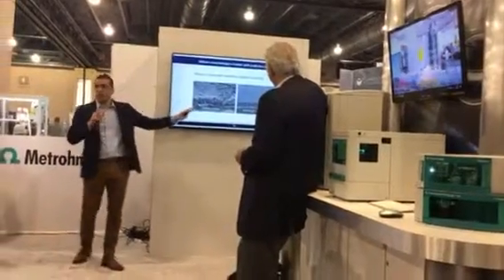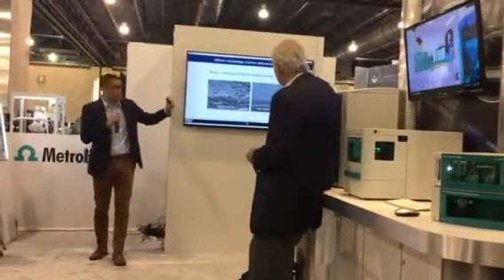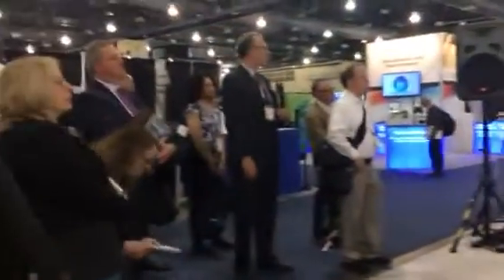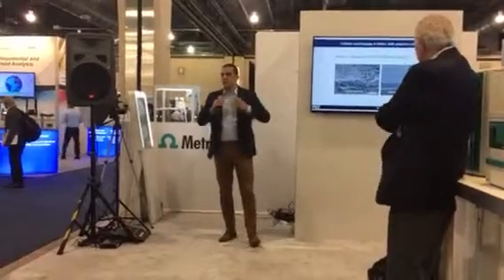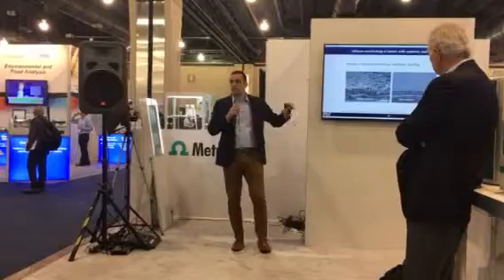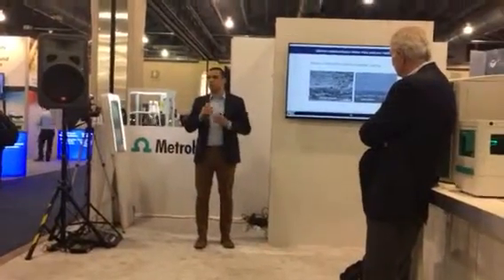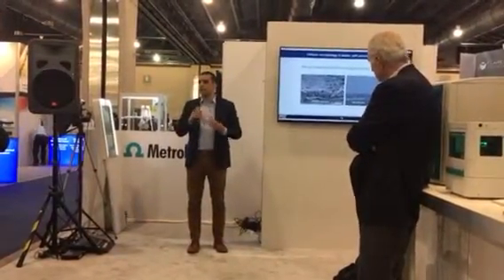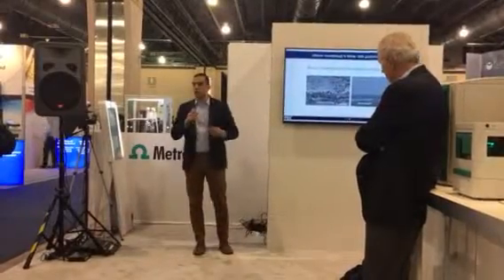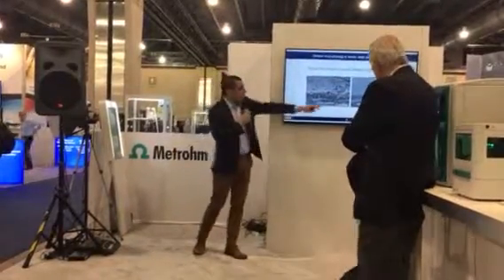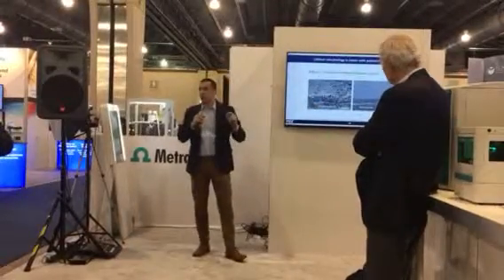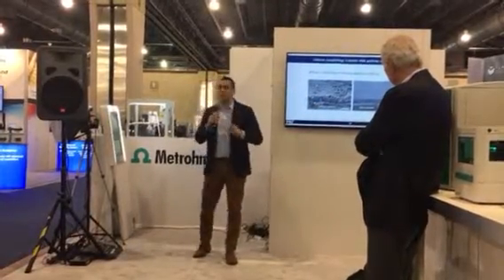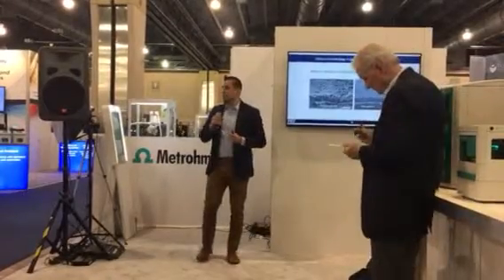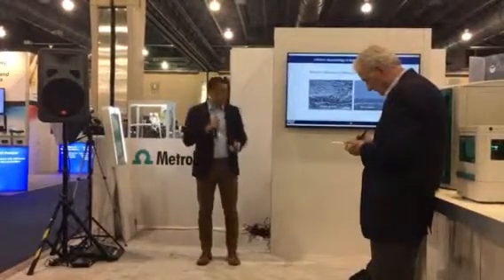Here's what an electron microscope image of these batteries look like up close. So this is on the micron scale after we've deposited the lithium metal into our battery. This again is without our polymer coating, and you can see it's very loose growth, very mossy structures, and that is what leads to the degradation. You have all of this surface area and this really poor quality deposition that leads to these dangerous problems that cause the fires, cause the short circuits, and cause these batteries to fail. However, with our polymer coating, you can see very thick, very dense deposition, so we have almost ideal cycling of these materials, meaning that they're very safe and very useful.